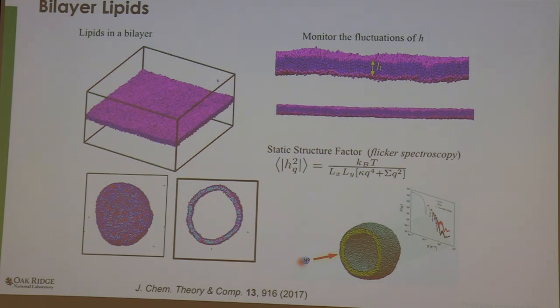Oh, this is just, yeah, so we have to compute the height fluctuations as a function of time, and you can relate it to this equation. There's a whole bunch of details that go in there, but that can be measured experimentally from neutron scattering, in small angle scattering, and that's shown over here. And if we can compute it, we can also predict it, and we can compare directly to neutron scattering. That's all that's for.